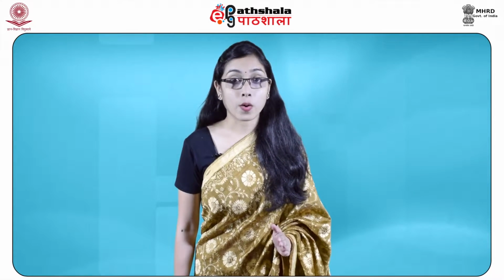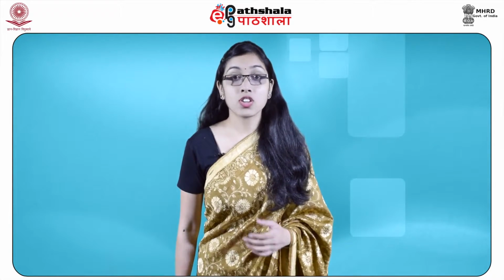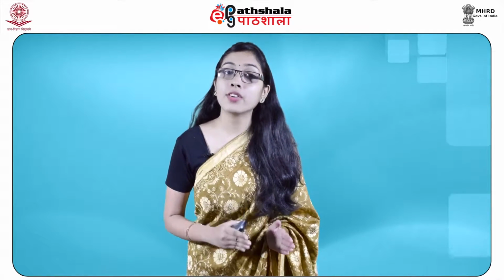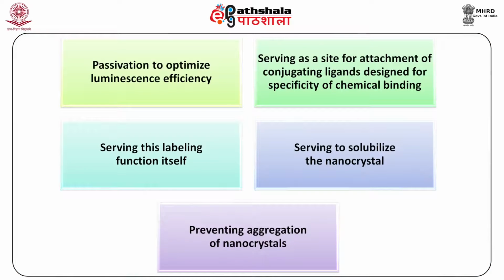They are typically encapsulated with zinc sulfide, silica, or an organic material. This capping is sometimes referred to as derivatization or functionalization, especially when an organic compound is involved, which is sometimes also referred to as a surfactant. The encapsulation amounts to covering the nanocrystal with a layer of material that may serve a variety of functions, for example, passivation to optimize luminescence efficiency, serving as a site for attachment of conjugating ligands designed for specificity of chemical binding, serving this labeling function itself, and serving to solubilize the nanocrystal and prevent aggregation of the nanocrystals.